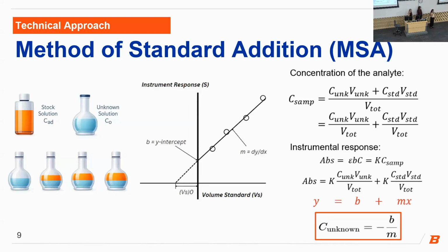The method of standard addition, or MSA, is a quantitative technique where we determine the concentration of an unknown analyte in a sample. In this method, constant volumes of unknown are placed into different samples, and then increased volumes of the standard solution are added, and finally we dilute them to a fixed final volume. The instrument response for each sample is measured, and the instrument response is plotted against the volume of standard added, and this will give us a linear relationship described by y equals mx plus b.